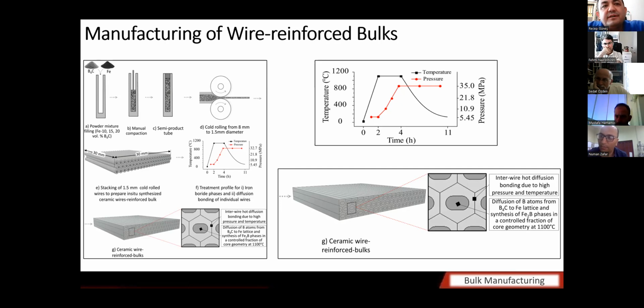What is the main purpose in obtaining the plates from wires? Why produce a plate indirectly? As I told you, we want a material which is strengthened at the wire level, and the wires are strengthened with iron boride phases. We want a material which is soft because of the presence of steel, which is recrystallized after the treatment and gives toughness to the material. At the same time, we want the material to be hard because of the presence of iron boride phases.